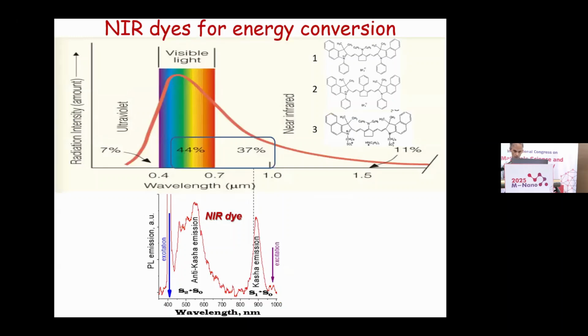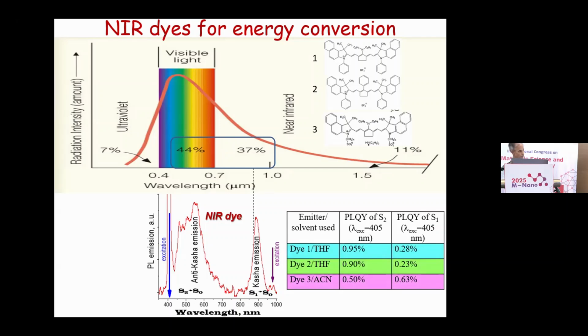Specifically, I will talk about infrared dyes, the structure of which is shown here. These dyes have a fundamental absorption and emission in the infrared. For example, this dye has emission near 900 nanometers. And we also can observe anti-Kasha emission of these dyes in the green part of the spectrum. But usually the quantum yield of these processes is very low. Here you can see the quantum yield of anti-Kasha and Kasha emission, which are usually less than 1%. So the problem is how to enhance the quantum yield of these processes.